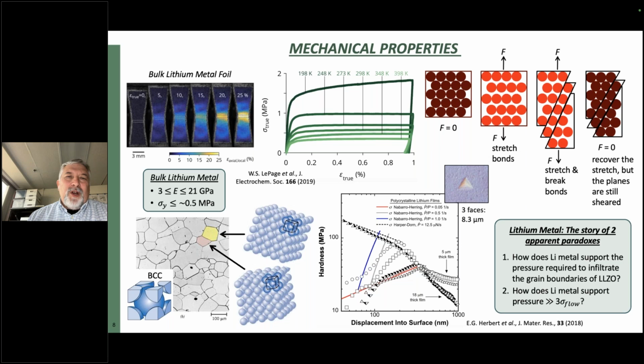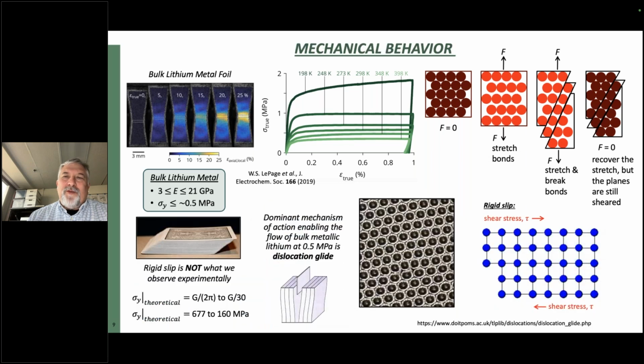All right, so I'm gonna offer a potential explanation, right? But before I do, I wanna loop back to this idea of rigid slip in bulk lithium, right? And this would apply to any bulk crystalline metal here. All right, so the idea there, at least what's pitched by this cartoon, again, for a bulk crystalline metal, this image actually does an okay job of illustrating what we observe experimentally, all right? But it turns out that this idea of rigid slip, which would be analogous to the shearing of this deck of cards, right?